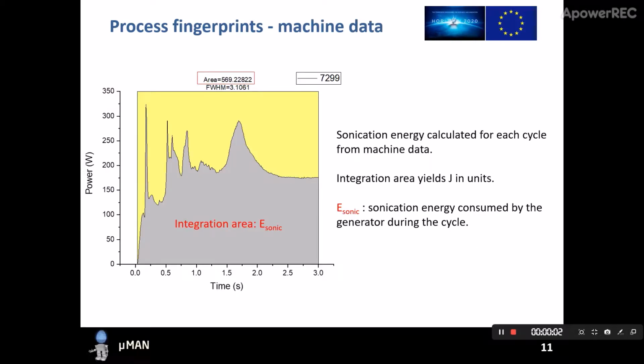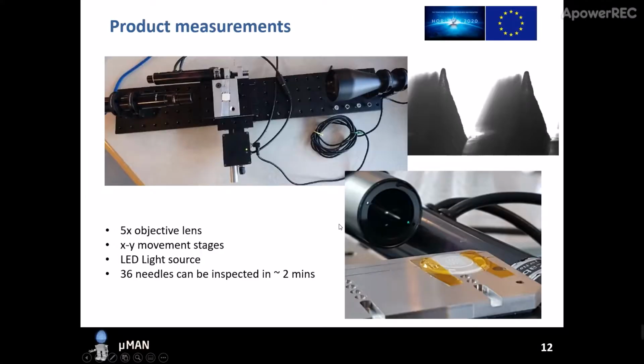We also capture machine data from the ultrasonic micromoulding machine, and in this case we have the power output of the ultrasonic generator versus time on the x-axis, and we calculate sonication energy for each cycle. So basically, if we integrate this curve, it will give us a number in units of joule, which is the sonication energy consumed by the generator for making one part, and we calculate it for each cycle, and we use this as a fingerprint for further analysis.